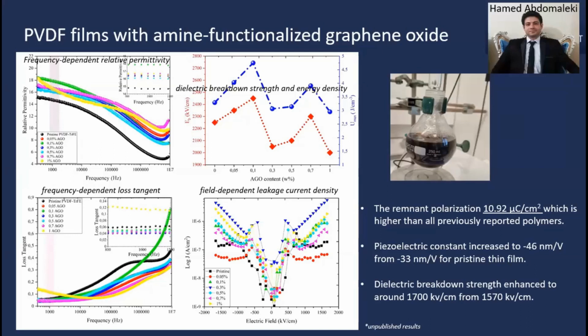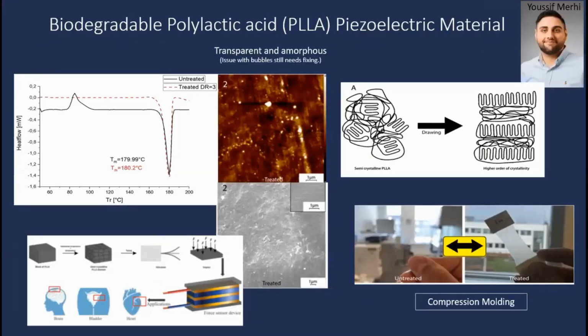So the idea here was to use different kinds of strategies. In another of the projects, again, we are targeting a material which is also a piezoelectric material. When we were working with PVDF, one problem that we have to deal with is that it needs poling. Poling is a process where basically you have to align the dipoles of the material. You have to put it inside a big electric field environment, put the material there, and then all the dipoles are permanently aligned. And then it's a good to go material.